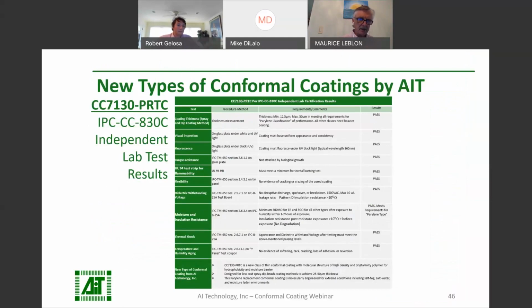Let's see, which one is it? The thickness measurement on glass plate under white and UV light must have uniform appearance and consistency. The third item down, on plate glass under UV light, coating must fluoresce under UV black light, typical wavelength. So yes, it does. And from firsthand knowledge, it does present itself very, very well. So you can tell your coating. It kind of gives you an idea of the thickness as well. Okay.